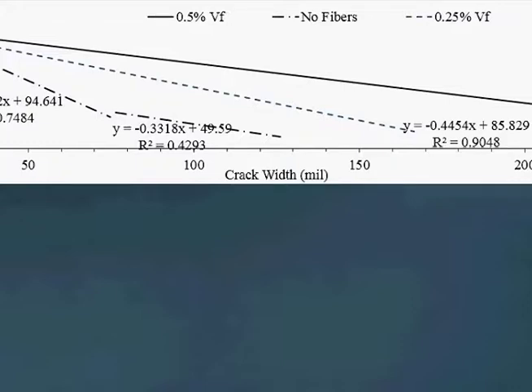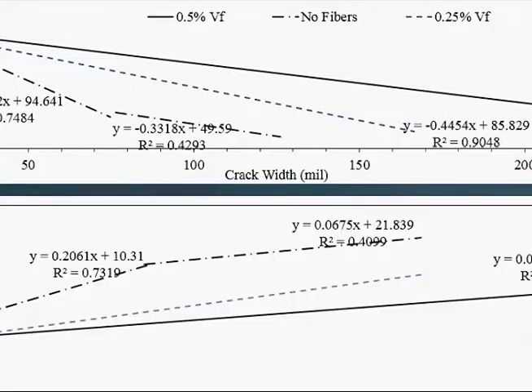So we've extended these results to find out. In general, you see here this curve is for plain concrete, then 0.25 and then 0.5. So if we use fibers, how much additional load transfer can we get from this correlation? Here this is the relation for the displacement, loaded side displacement. So if we want to use fiber and the DOT or the agency decides, okay, we probably look for 20% additional load transfer, or 30% maybe, we can look at this kind of correlation and find out what kind of dose we want.